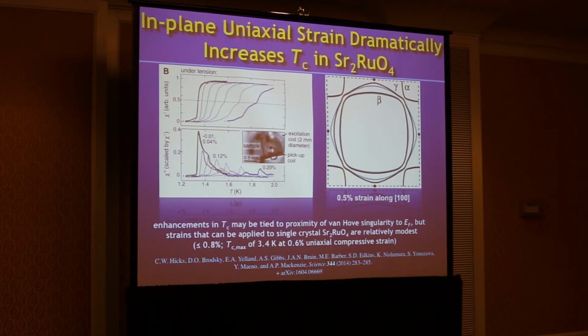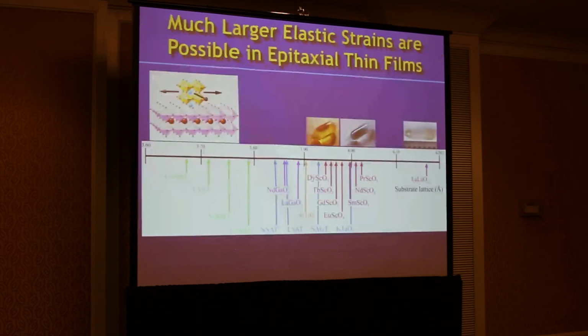But maybe there are other ways to impose even larger strains. And that's, again, where thin films can come in. If you have a very thin film, the volume free energy associated with straining this thing is quite small. So you can strain to much larger amounts, so percent levels, and I'll show you that right now.